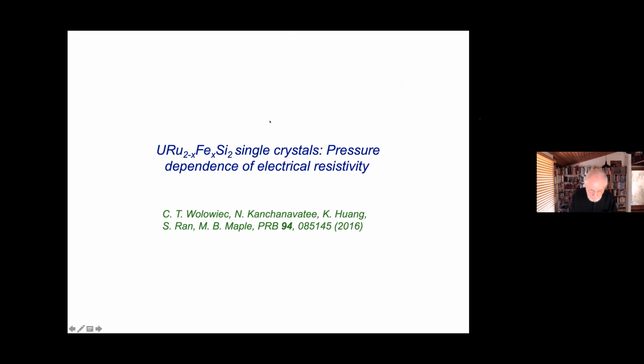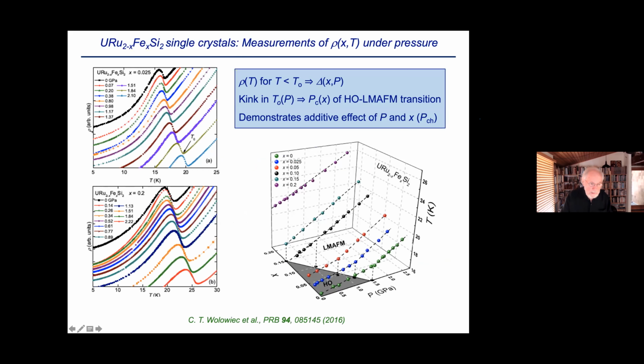Okay, and then we've done work on the pressure dependence of the electrical resistivity for iron, and then recently work on osmium, which I'll come to towards the end. That was also recently published in PNAS. And so here basically what you find is that if you measure the resistivity under pressure in a piston cylinder cell, you can see distinct features due to the hidden order and the antiferromagnetic transitions shown here. And then if you take these temperatures and plot them versus pressure at various iron concentrations, then for the pure compound, you see this is the hidden order phase boundary.